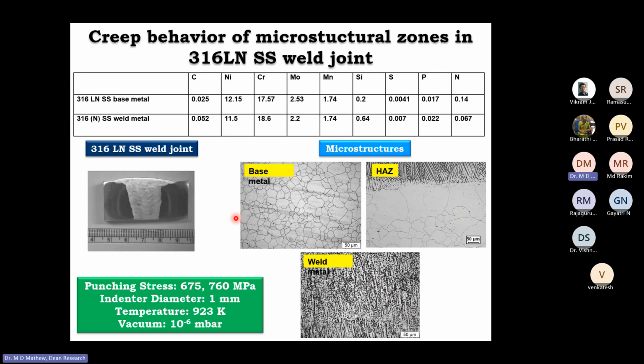I mentioned that one of the unique advantages of this impression creep test is that you are able to determine the creep properties of various microstructural zones of a weld joint. What you see here is a weld piece. You have the base metal, you have the weld metal. So this is the microstructure of the base metal, equiaxed grains. And the weld is dendritic structure with delta ferrite, some 4 to 8%.